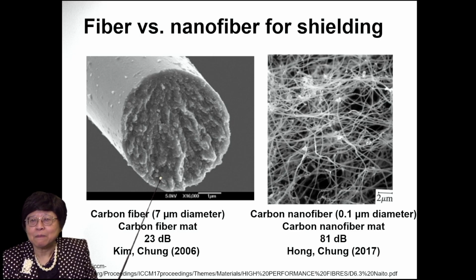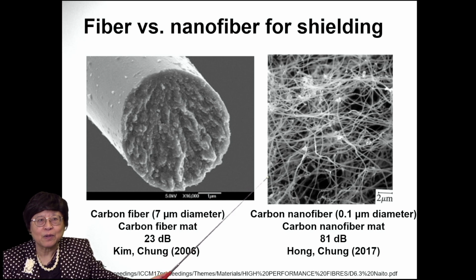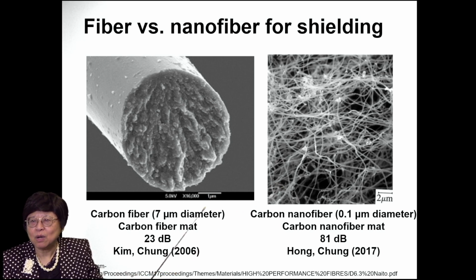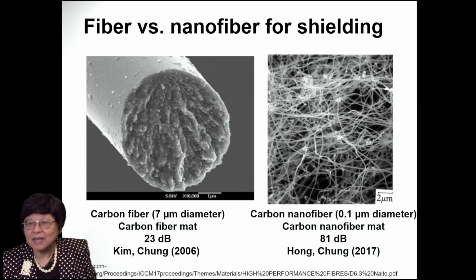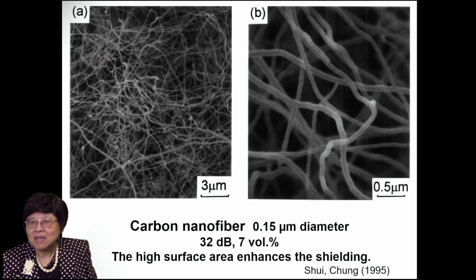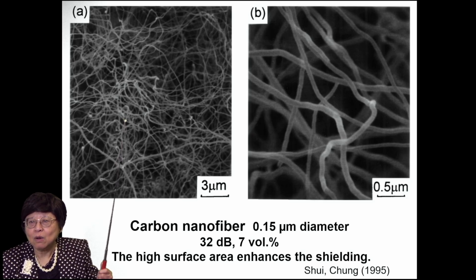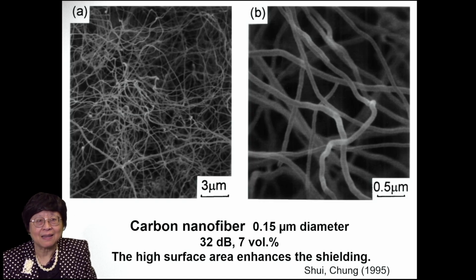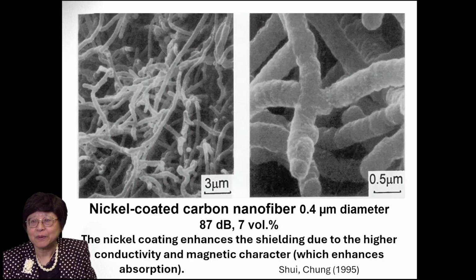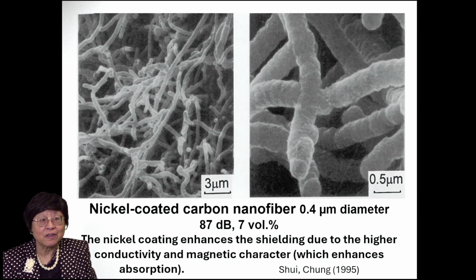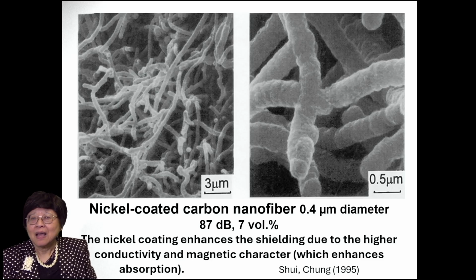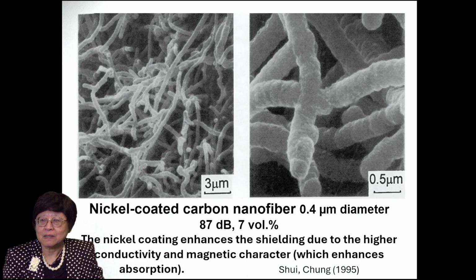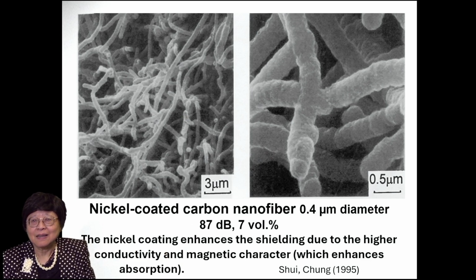Shown on the left is a microfiber, that's the usual carbon fiber. On the right is carbon nanofiber. And we show that by going from micro to nano, we can improve the shielding quite a lot. This shows the carbon nanofiber, low MAG here and high MAG here. But we can improve this further by depositing nickel onto the carbon nanofiber. The nickel is a metal, so it's very conductive. Also, it's magnetic. And this is low MAG and high MAG view of the nickel-coated carbon fiber. And this we reported back in 1995, and it's still among the very best fillers for EMI shielding.